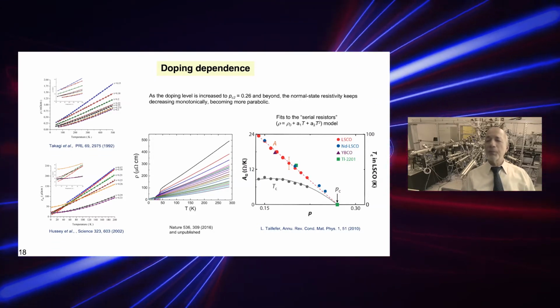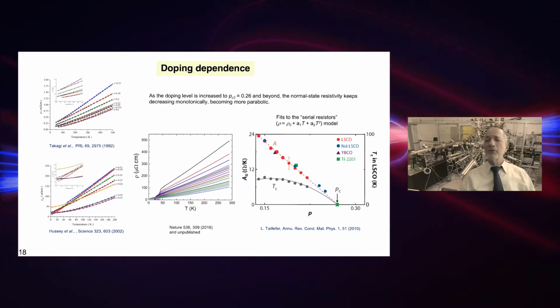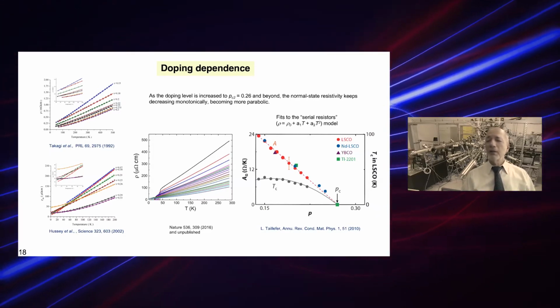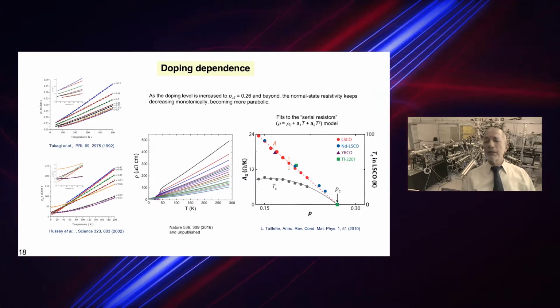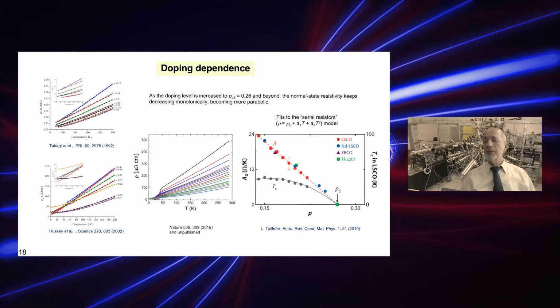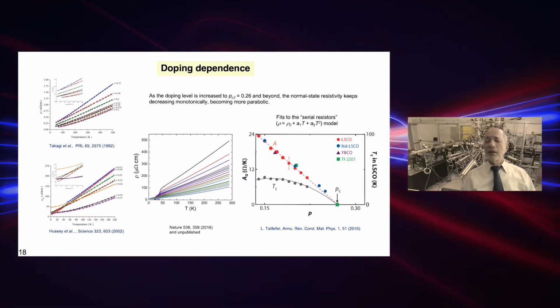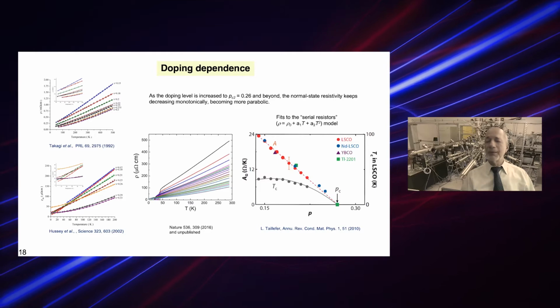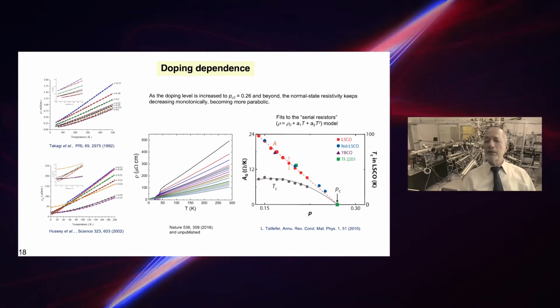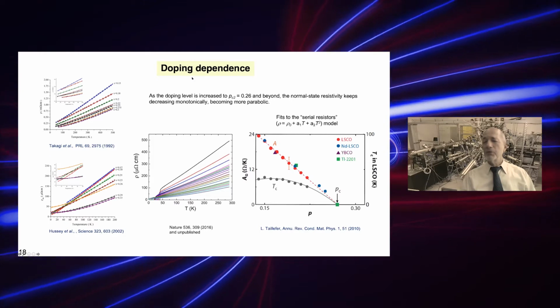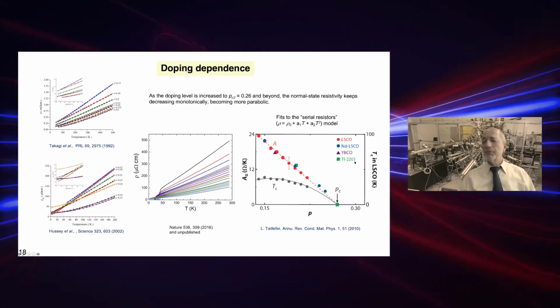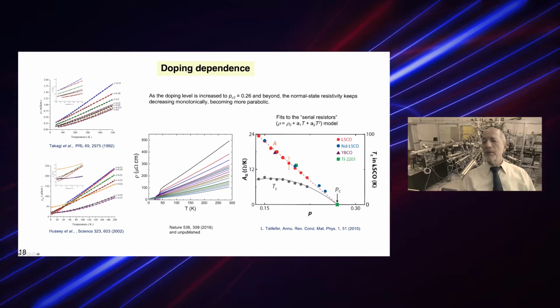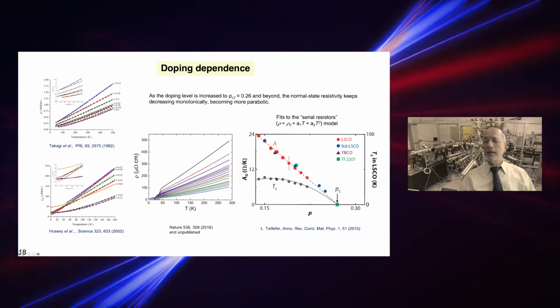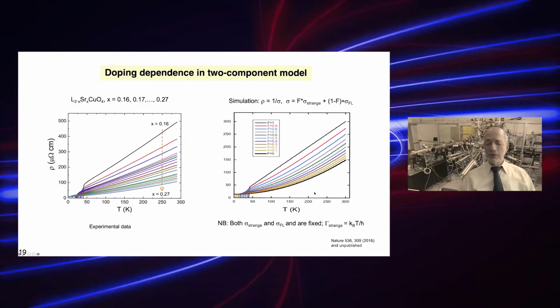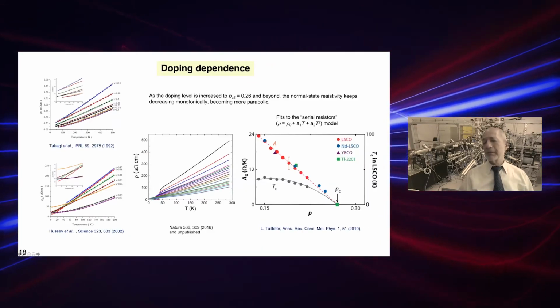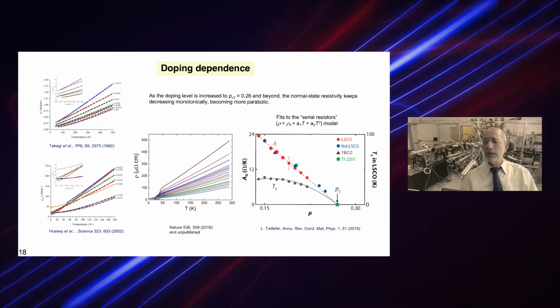And as a function of doping, this coefficient A, which is A1 in my formula, was found to decrease linearly and disappear right at the edge of the dome. I have some issues with this plot, one of which is that these are actually two ordinates. The TC, which is the dome, has dimension of Kelvin, while A has dimension of ohm over Kelvin. So you can change these scales arbitrarily.